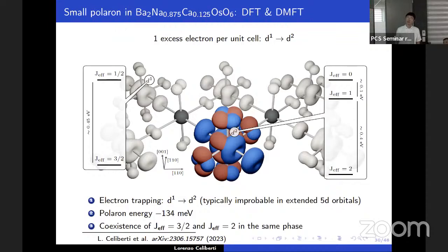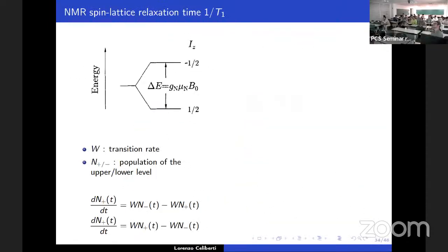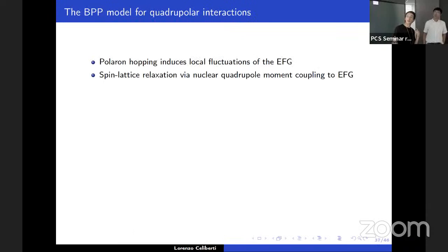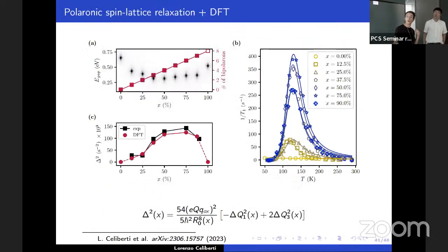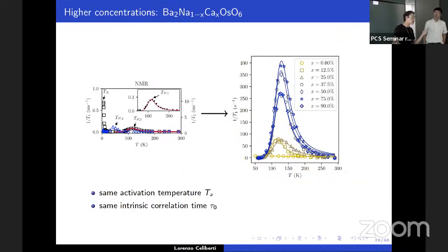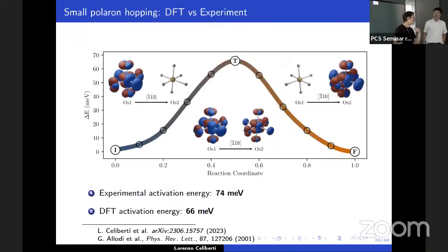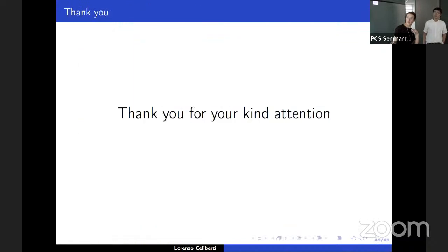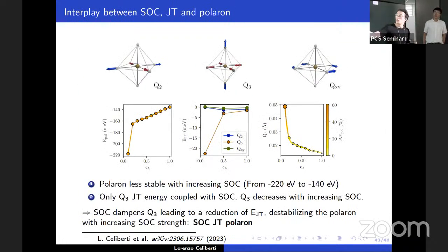And this is also why the impurity model calculation that I showed you at the beginning also agrees with the calculation we did. When I showed you these two trends, if you remember, they correspond to the calculation made by Streltsov with exact diagonalization on a Jahn-Teller impurity. They have the same qualitative trend. It's exactly the same, because this polaron basically constitutes a Jahn-Teller impurity in this lattice.